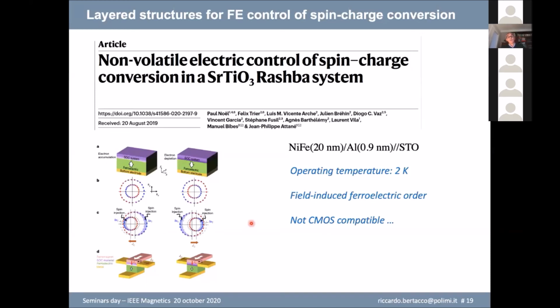The operating temperature is 2 Kelvin. It's not a real ferroelectric material. It's a field-induced ferroelectric order. And obviously, it's not CMOS compatible. What I'm showing you today is that in germanium telluride, in principle, you are CMOS compatible. You are not dealing with a field-induced order, but it is really a ferroelectric material. And the operating temperature for this spin-to-charge conversion is 300 Kelvin, which means room temperature.